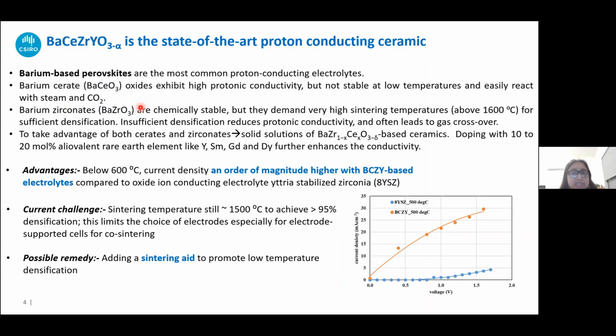However, they are not stable at slightly lower temperatures, and they easily react with steam and carbon dioxide. Barium zirconates, however, are chemically very stable, but they demand very high sintering temperatures for sufficient densification. And without densification, there can be gas crossover, and that also reduces the proton conductivity. Now, to take advantage of both the cerate and the zirconate, the commonly used material is a solid solution of barium cerate and barium zirconate.